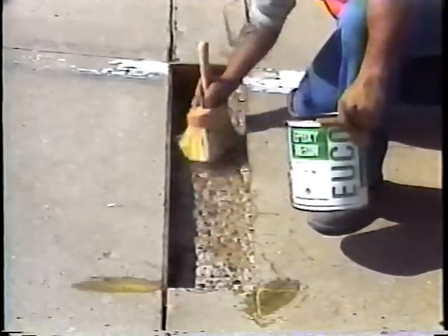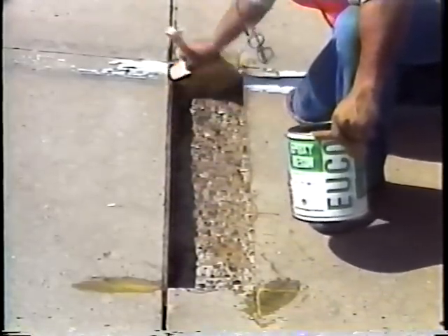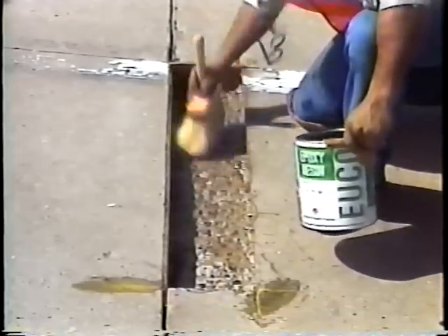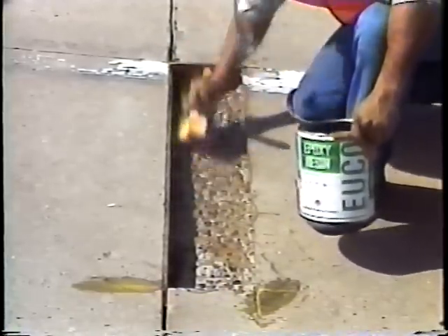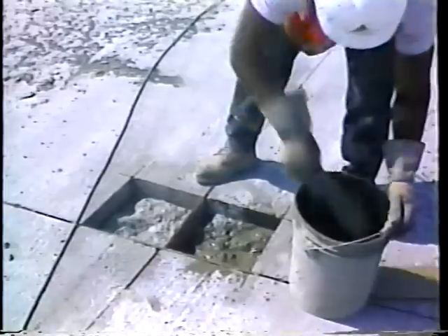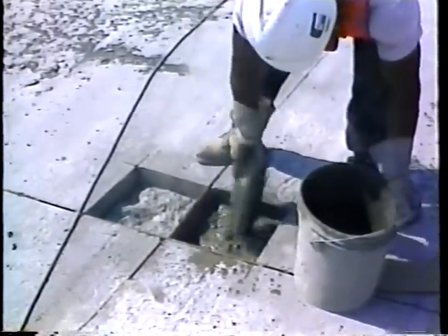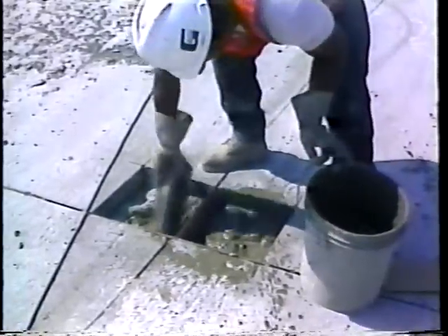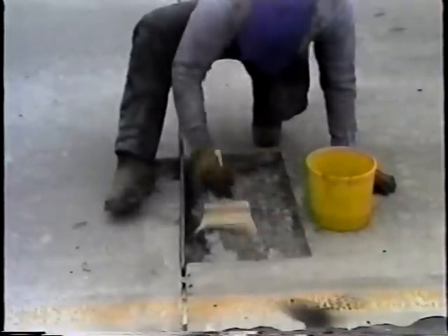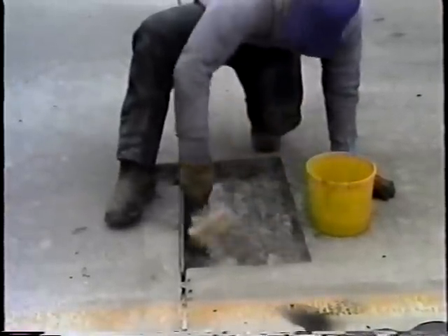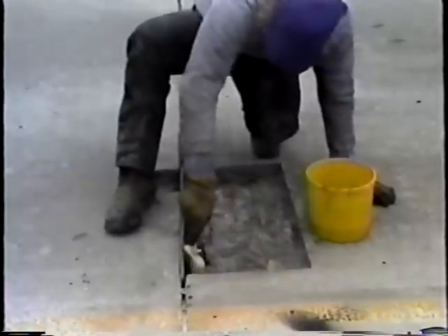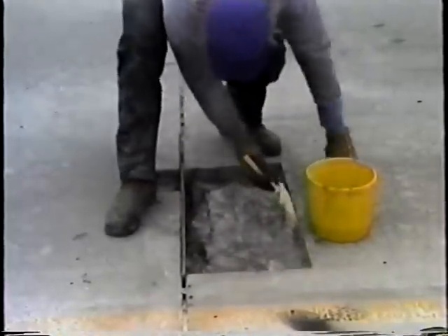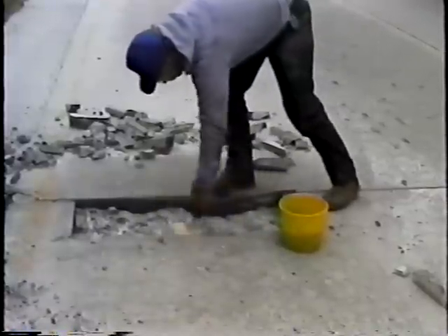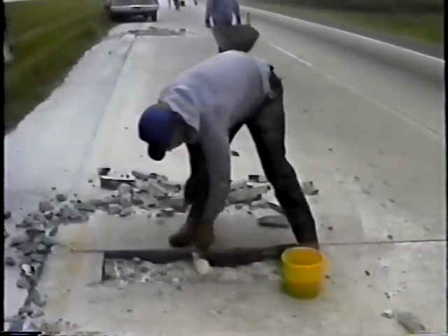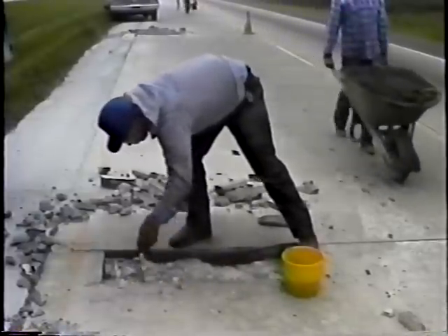Bonding may or may not be required as the last step in surface preparation. It is required when PCC and some of the proprietary materials are used. For these, epoxy has proven to be a successful bonding agent. Sand cement grouts are another type of bonding agent, but are not recommended for rapid setting materials. Bonding agents should be applied according to the manufacturer's recommendations by brushing or spraying. If epoxy is to be brushed on, it's best to use a stiff bristled brush. Spraying is more suited to large areas. In both cases, though, the material has to be applied completely and uniformly to the bottom and sides of the repair area just prior to placing the concrete.